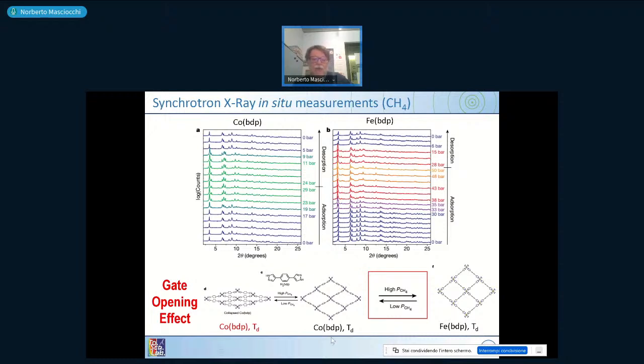metal organic frameworks, which show a gate opening effect. Without going into the discussion, I want to show you that this material from 0 bar pressure to 29 bars with high pressure and back is flexible because it expands, and the one with iron expands even more. And by removing the pressure, it can be shrunk again.